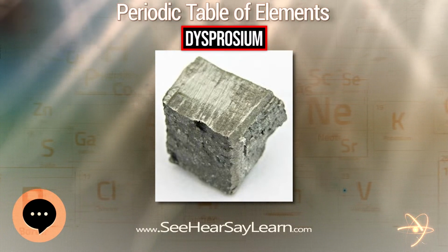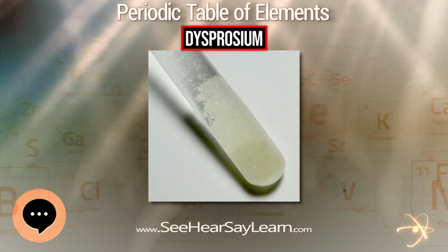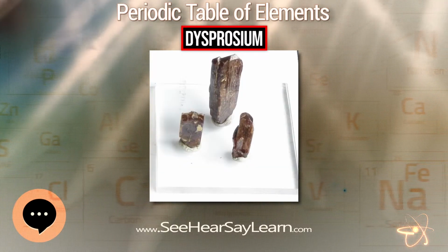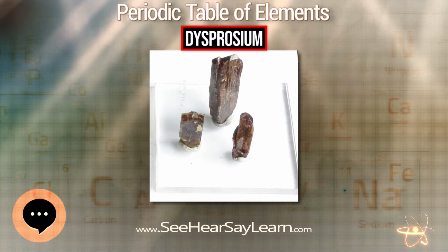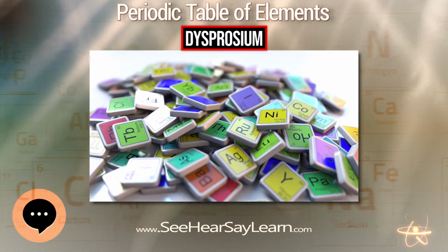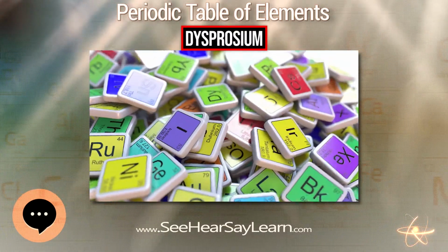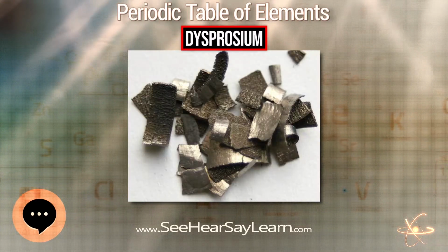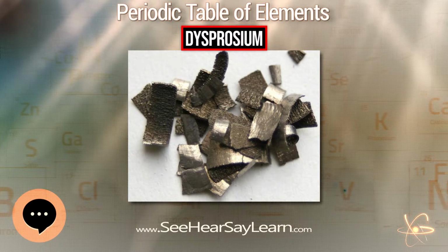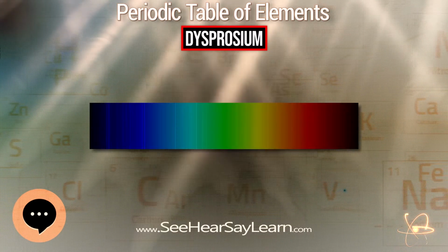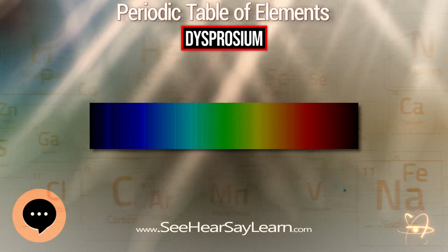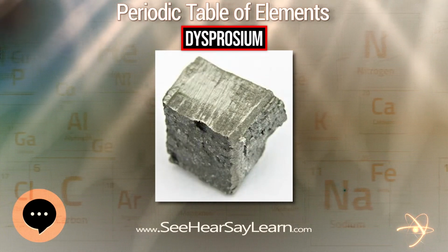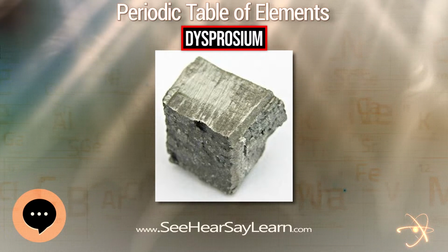Nanofibers of dysprosium compounds have high strength and a large surface area. Therefore, they can be used to reinforce other materials and act as a catalyst. Fibers of dysprosium oxide fluoride can be produced by heating an aqueous solution of DyBr3 and NaF to 450 degrees C for 17 hours. This material is remarkably robust, surviving over 100 hours in various aqueous solutions at temperatures exceeding 400 degrees C without redissolving or aggregating.